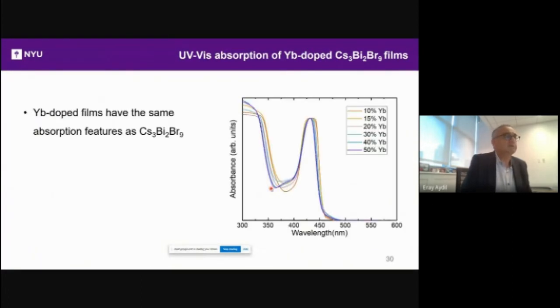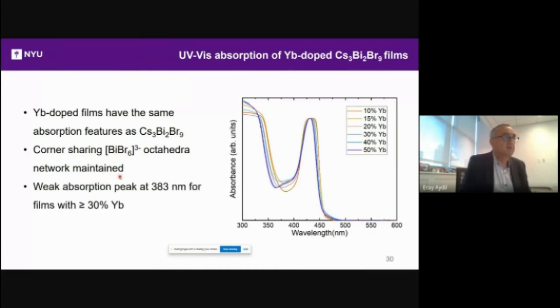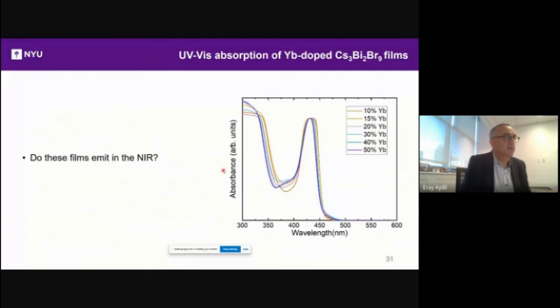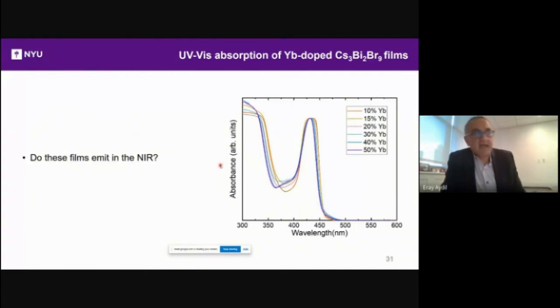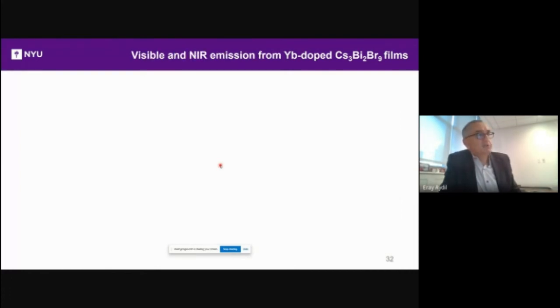Okay, the UV-vis absorption, there's not much of a change. It peaks still in the same place, so that is a sign that the corner sharing of this BiBr6 octahedra network is maintained. There's a little bit of weak absorption at 383 nanometers for films with greater than 30% ytterbium. We think that there might be some of the 316 phase appearing. So the question is now, do these films emit in the near infrared? And the results are very encouraging.